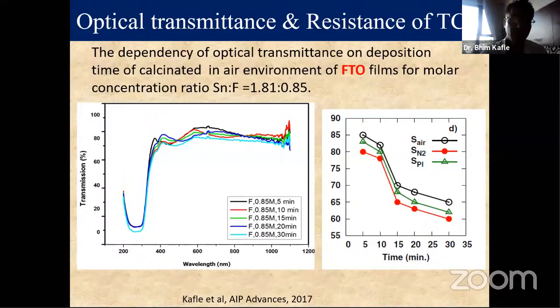Sorry. So you can look here at the transmission. This FTO, fluorine doped tin oxide, absorbs UV light, but it transmits all the visible light. You can see here very nicely that above 80%, up to 85% transmission, was achieved.